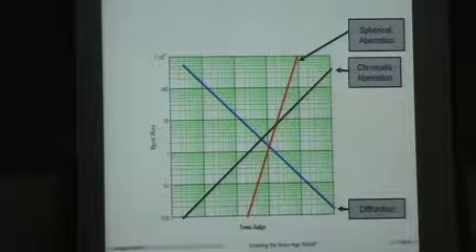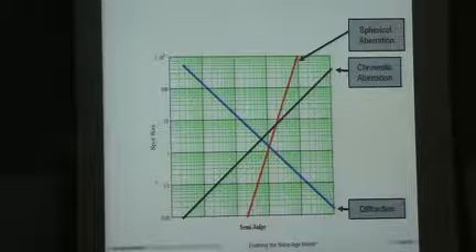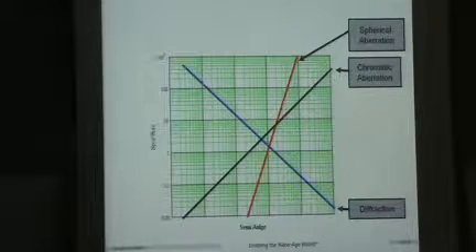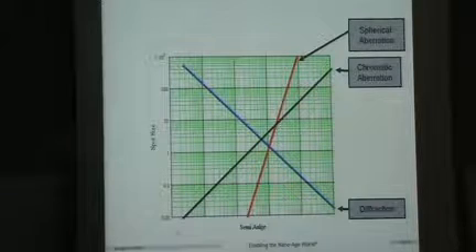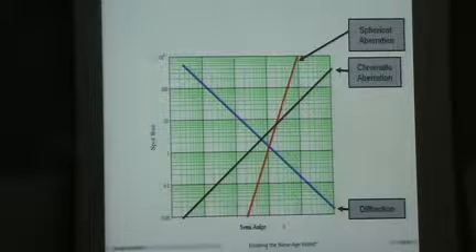The probe forming, I mentioned, can be quite good. This is a common diagram if you're used to thinking about how a SEM can get its best probe size. The vertical axis is the spot size in nanometers. The horizontal axis is a semi-angle, or what you can achieve with a big aperture or a small aperture. This is the big aperture end. At big aperture sizes, you're limited by spherical aberration. Make your aperture smaller, you're limited by chromatic.